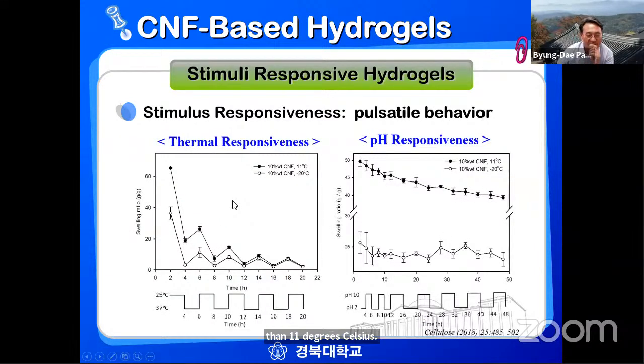This is what I'm going to tell you, that we prepare the hydrogels and then put them in 2 different temperatures, 25 and 37 degrees Celsius, for 2 hours, and then measure the swelling ratios at each step. As you see here, as time increases, this is 11 degree polymerization, minus 20 degree polymerization temperature, and 10% CNF. You know, the swelling ratios go up and the shrinking like this. We can have this kind of response, thermal response polymer. Up to, I would say about 10 hours is okay.